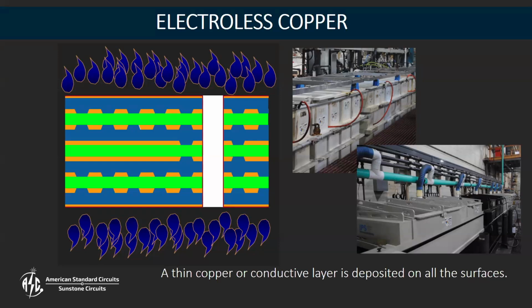The first part of that process is what we call an electroless copper deposition, which is a catalyzed reaction. Its whole job is to put a thin, somewhere in the neighborhood of 25 to 50 microinches of copper inside of those holes, whether it be a blind via or a through hole. And that is just going to be a sufficient amount of copper to accommodate the electroplating of copper down the road. So this chemical process makes sure that all the copper surface is clean, and then it puts this small amount of copper into the holes.